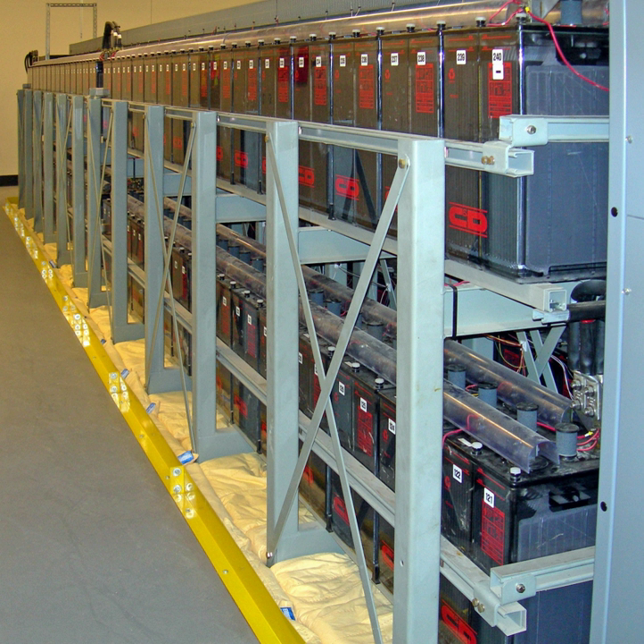Cell reversal can occur under a number of circumstances, the two most common being: when a battery or cell is connected to a charging circuit the wrong way around, and when a battery made of several cells connected in series is deeply discharged. In the latter case, the problem occurs due to the different cells in a battery having slightly different capacities. When one cell reaches discharge level ahead of the rest, the remaining cells will force the current through the discharged cell. Many battery-operated devices have a low voltage cutoff that prevents deep discharges from occurring that might cause cell reversal.